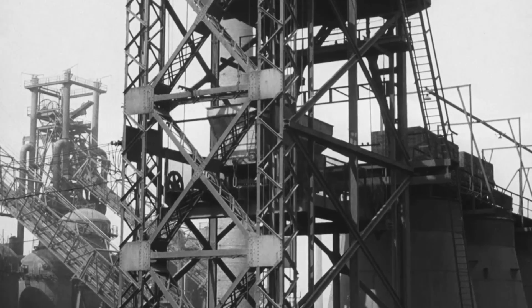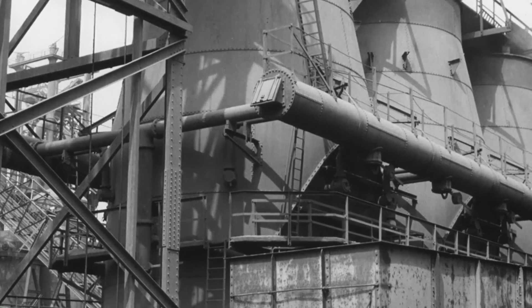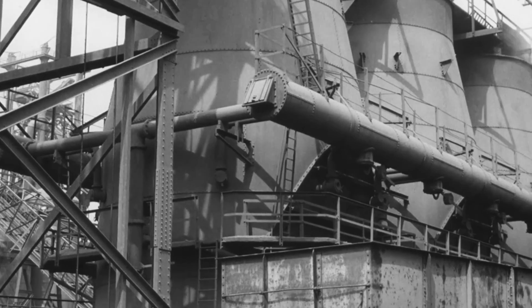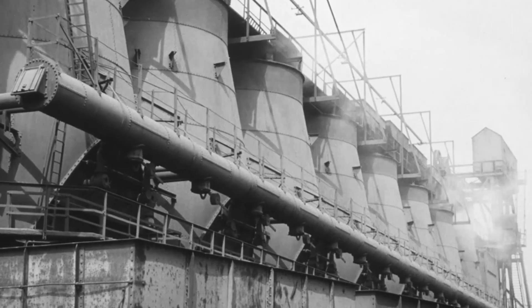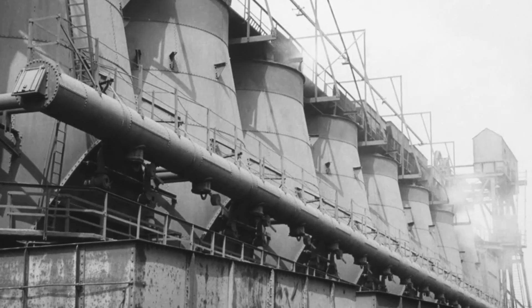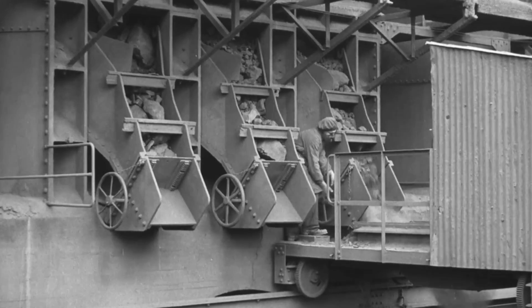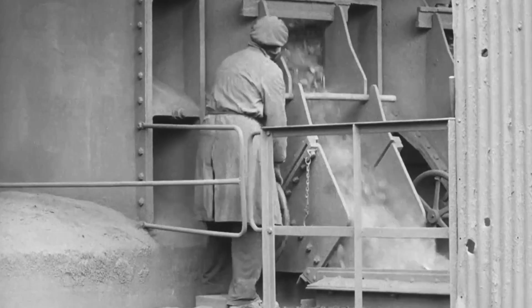When this is carried out at the plant, alternate layers of ore and coal slack are loaded into kilns, and a slow burning process takes place. This process takes about a week to complete, and the ore is then ready for smelting. The treated ore is drawn off from the bottom of the kilns into hopper wagons, from where it's emptied into bunkers until required for furnace charging.